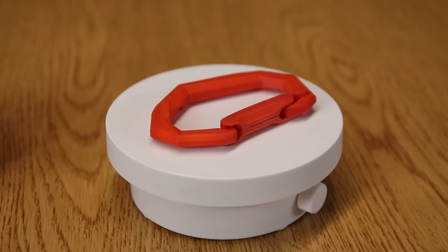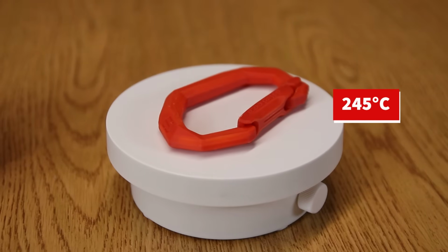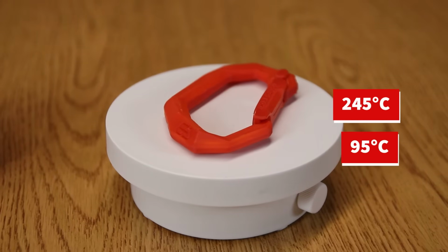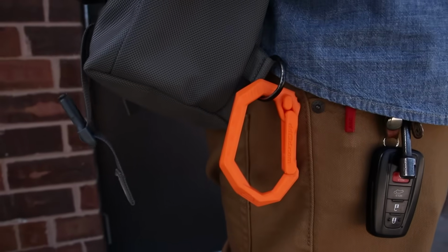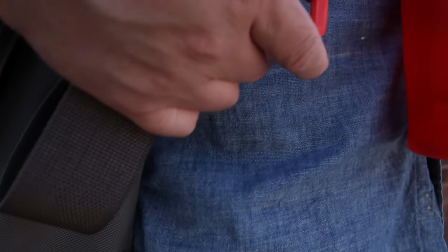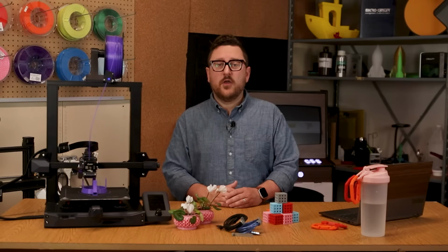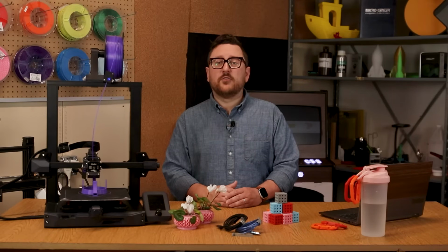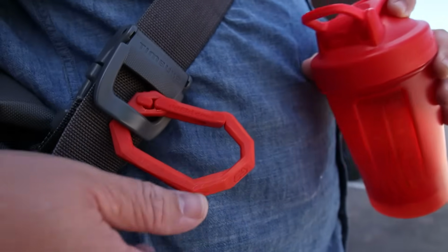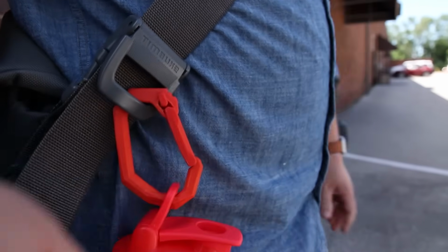The featured print here was done at 245 degrees Celsius for the hot end and 95 degrees for the bed. We did experience some very minor warping on the bed, which could be helped by increasing the temperature or potentially using some adhesive such as Magigoo. Ultimately, this carabiner came out great and functions as expected.